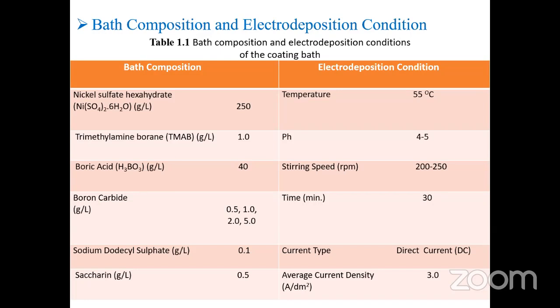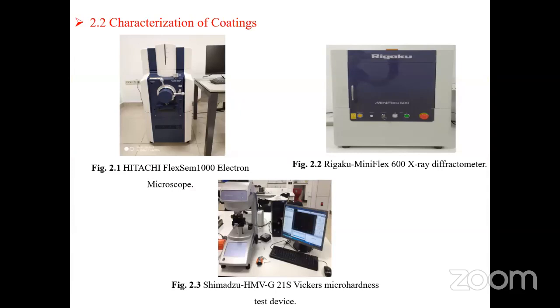For the study, our working temperature for the coating bath is 55 degrees centigrade, and the bath is mixed at about 250 RPM during the process. I use direct current, and the average current density in this current type is 3 ampere per decimeter square, and the work time is 30 minutes. Characterization of coatings.